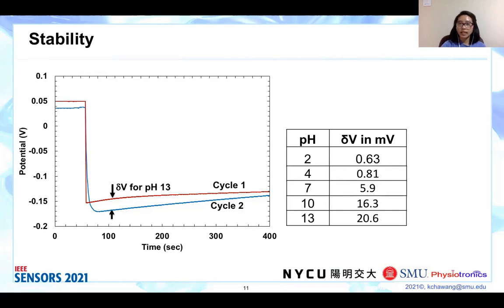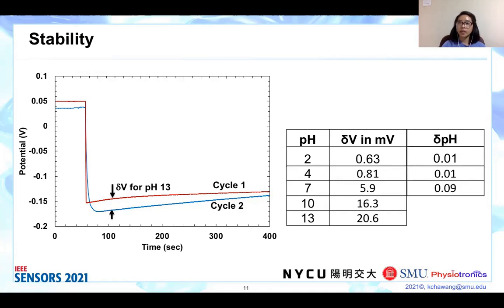Using calibration curves at pH 2, 4, 7, 10, and 13, the corresponding pH deviations are 0.01 at pH 2, 0.01 again at pH 4, 0.09 at pH 7, 0.26 at pH 10, and 0.33 at pH 13.